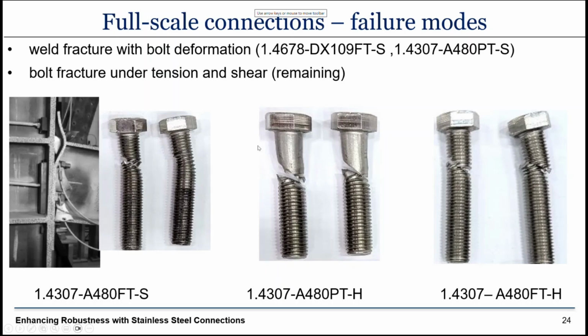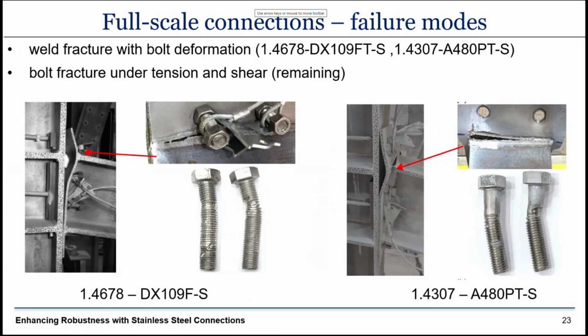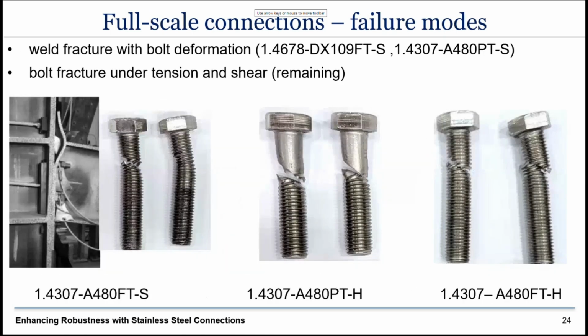And the remaining 3 specimens failed with bolt fracture under tension and shear. You can see here that that happened for fully threaded bolts and partially threaded bolts as well, and also under static conditions and under high loading speed conditions. By high loading speeds, in this case, we applied a loading speed of about 10 millimeters per second, if I remember correctly. For the top and seat angle connections, we reached up to 400 millimeters per second.